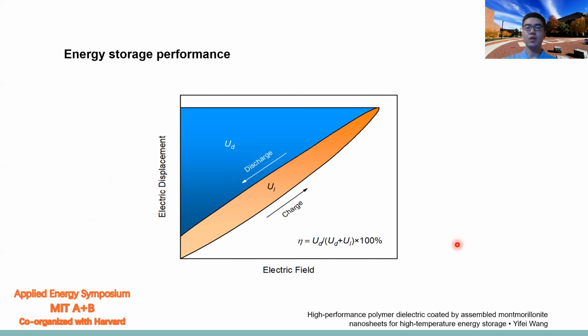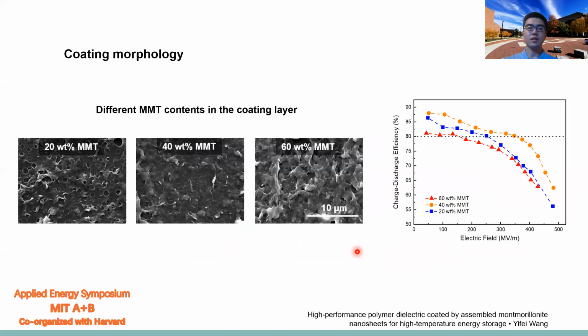From the D-E loop measurement, we can extract the discharge energy density and the energy loss, and we can calculate the charge-discharge efficiency by this equation. At first, we checked the influence of MMT content on the dielectric energy storage performance. We gradually increased the MMT content in the coating layer, where we also use some PVB as the binder to combine all these nanosheets together.